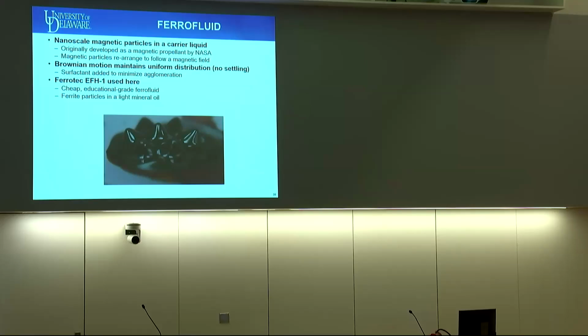But the big advantage of a ferrofluid is that because the magnetic particles are very, very small, they're able to maintain a uniform distribution. So you don't get settling, you get a nice uniform distribution of magnetic particles. And typically we do add a surfactant to minimize agglomeration. You don't want them to agglomerate into larger magnetic particles that'll then settle to the bottom. The work that I'm going to be showing here is just using a cheap educational grade ferrofluid called Ferrotec EFH1. That's just ferrite particles in a light mineral oil. So a very common material that is relatively low cost.